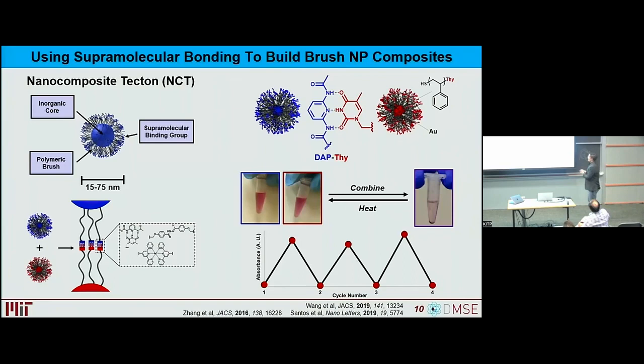So if I have these particles that are coated in DAP or thymine-terminated polystyrene, in organic solvents like toluene, they're going to be more or less indefinitely soluble. But as soon as I combine them together, this complementary pair causes them to assemble and precipitate out of solution. I can break them apart by heating them up. I can reassemble by cooling them down. So this is a thermally driven process. It's not evaporation driven. It occurs in solution and it is easily reversible.